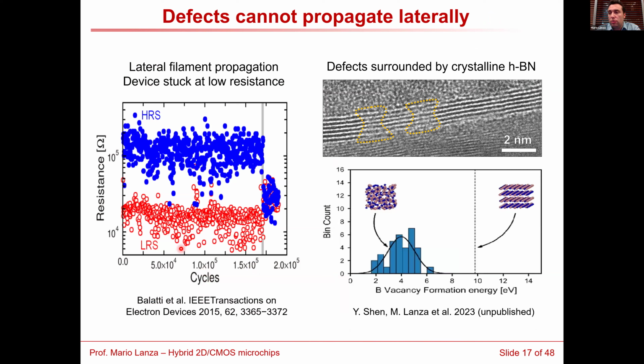So when you use the memristor, normally you switch it between the low resistive state and the high resistive state for thousands of cycles. But at the end, it normally happens that this conductive filament propagates laterally and it cannot be recovered anymore. And if it cannot be recovered anymore, you end up with a permanent low resistive state, which is what you see here.